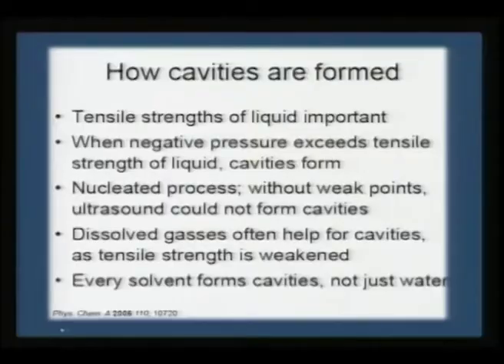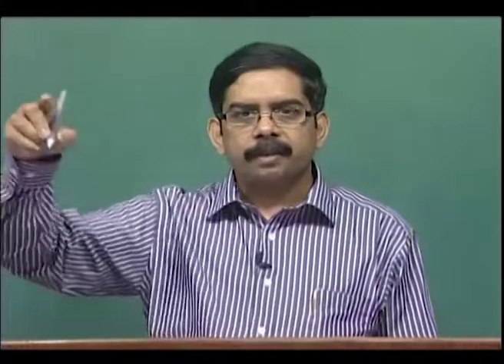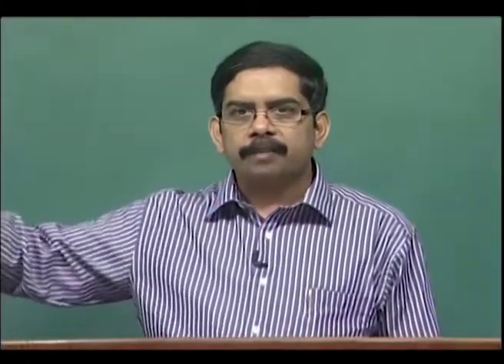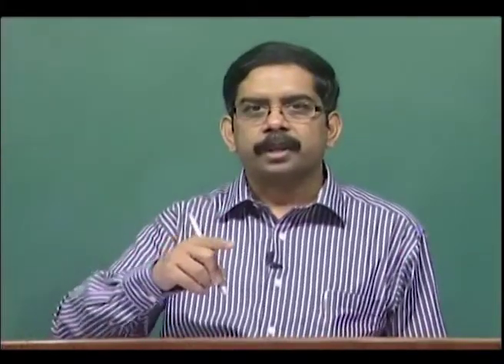Now how are cavities formed in solvents? They are mainly dependent on the tensile strength of the liquid. So depending on the tensile strength of different solvents, cavities are formed. When negative pressure exceeds the tensile strength of the liquid, cavities are formed. So there should be a negative pressure during these ultrasound waves. You have a compression and a rarefaction wave. When you have a negative pressure which exceeds the tensile strength of the liquid, then immediately it results in a cavity.